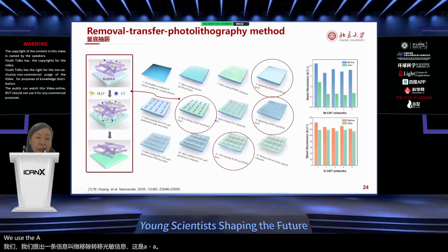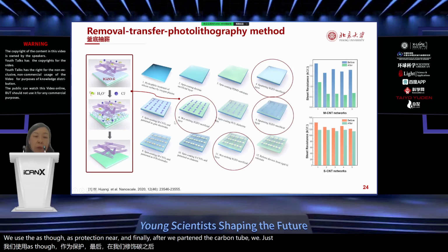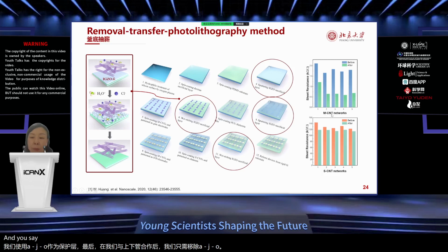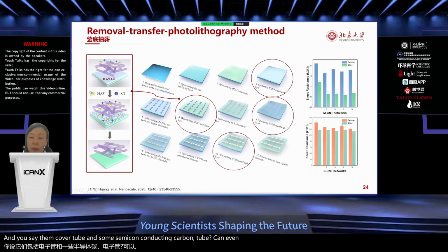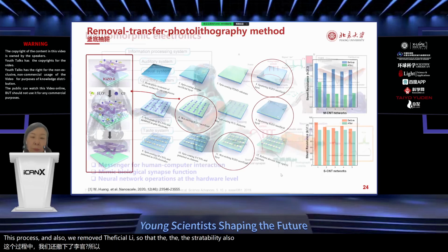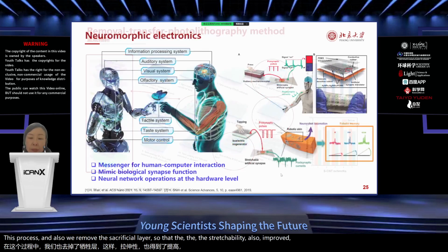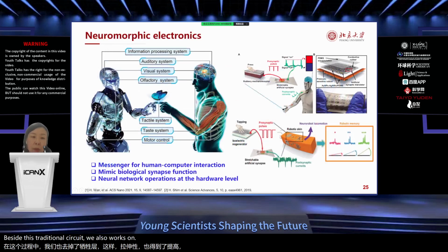We use IGZO as a protection layer, and finally, after we pattern the carbon nanotube, we just remove the IGZO. You see the metallic carbon nanotube and this semiconducting carbon nanotube has even better resistance after this process. And also we remove the sacrificial layer so that the stretchability is also improved. Besides this traditional circuit, we also work on some neuromorphic transistors.